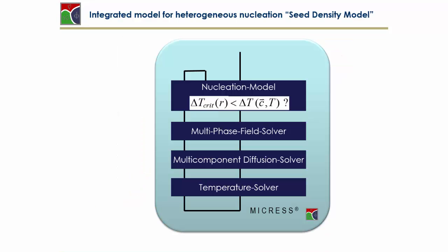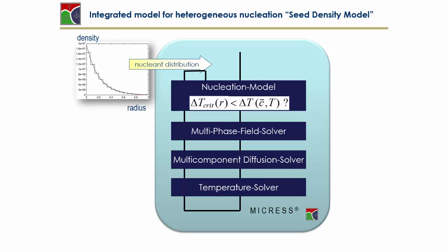It is important to note that nucleation cannot be treated really at the scale of individual atoms forming the initial nucleus, but in the multiphase field model we use classical nucleation theory where we've got a distribution of particles with different radii. Depending on the radii, each particle provides a potential nucleation site, and the smaller the particle, the higher undercooling is needed to activate.